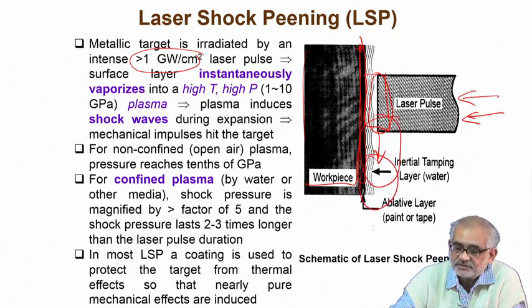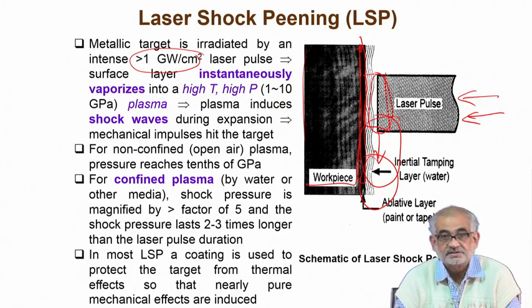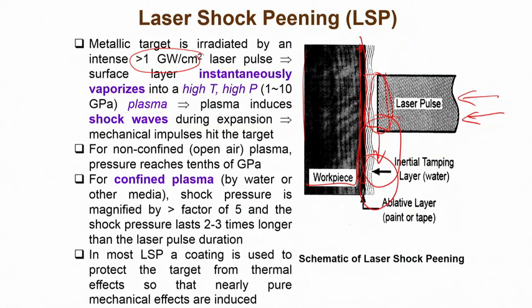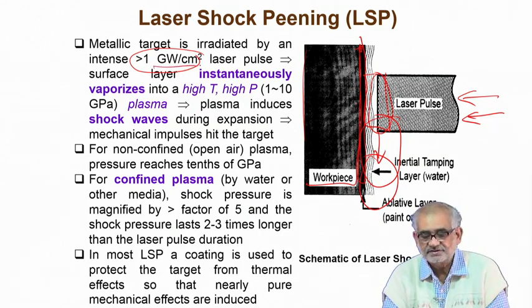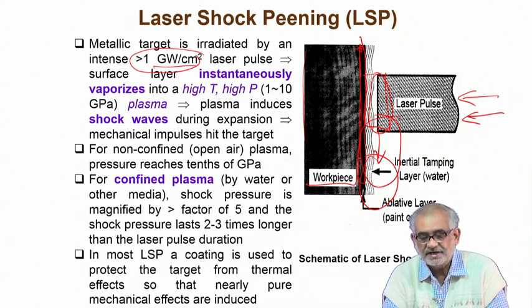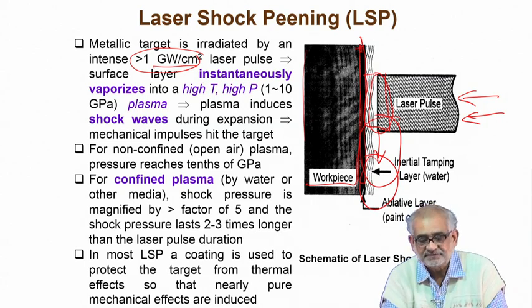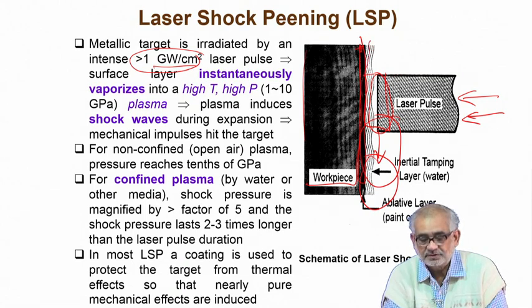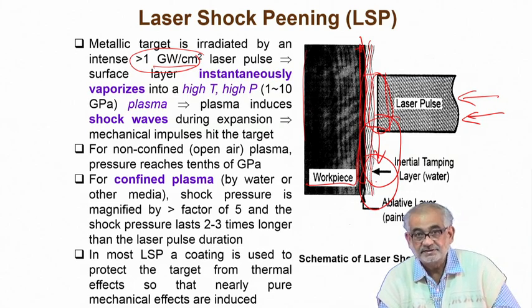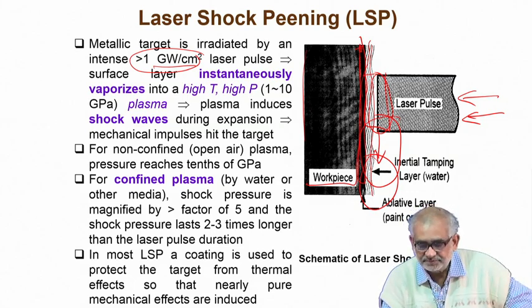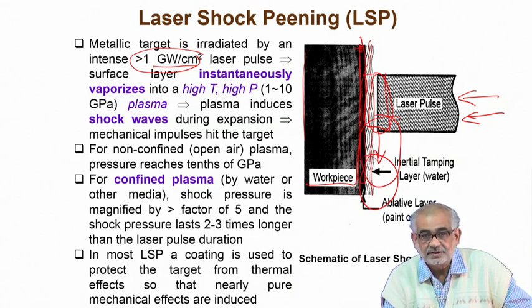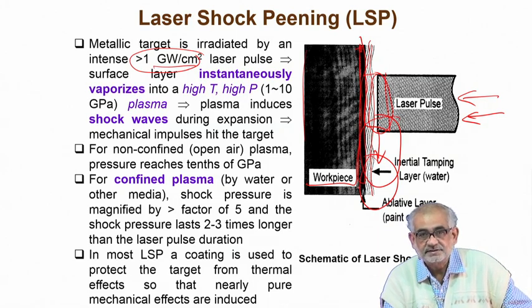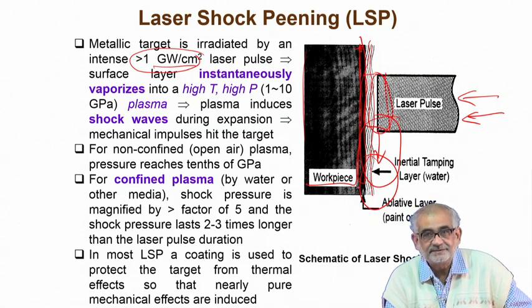Even if the laser beam is small, you can cover a much wider or longer surface area. When you irradiate such very high power density onto the surface, the coating below the tape gets vaporized instantly. When it vaporizes, it tries to expand, but because of the cover applied on the other side, the wave created between the tape and the work piece experiences an extremely high level of shock wave, and this shock wave is able to deform a very thin depth from the surface.